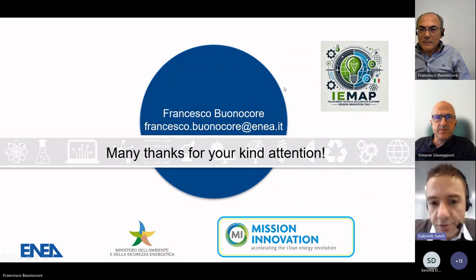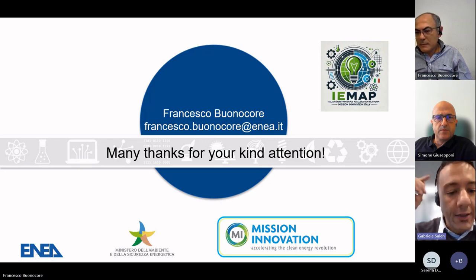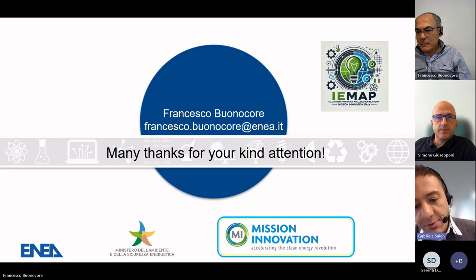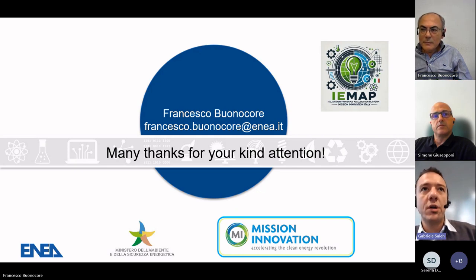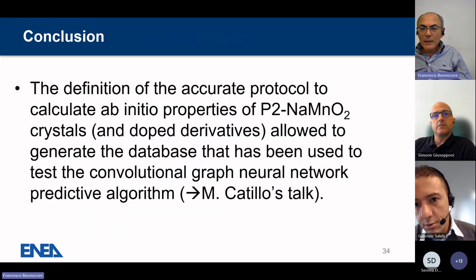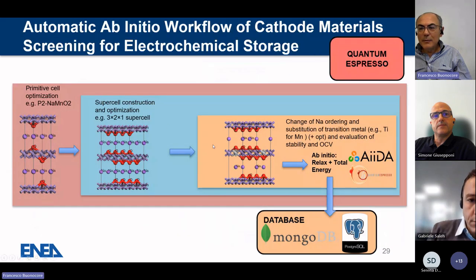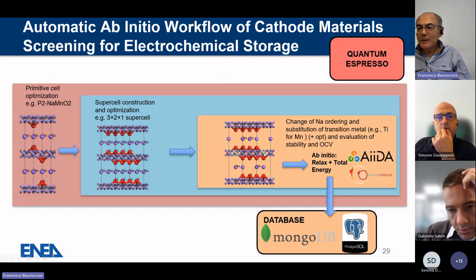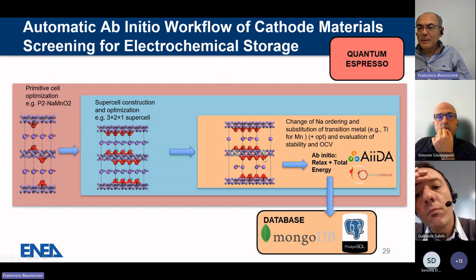Yes, thank you for your talk. Very interesting. I have a curiosity. When you do these high throughput ab initio simulations, basically you substitute the transition metal in the compound. And so you assume that all the compounds will have that layered structure of the initial compound that was, I think, manganese, sodium, oxygen. So you assume that the structure will be the same and you just substitute the transition metal. Is that correct? Yeah, it's correct. I should go back. Yeah, this is the procedure. Yes, you assume that the crystal has the same structure. You don't have phase transition. You just examine this case. Yes, indeed, it's this way.